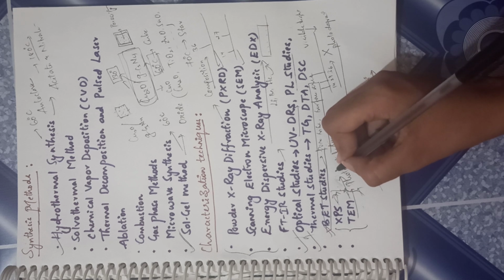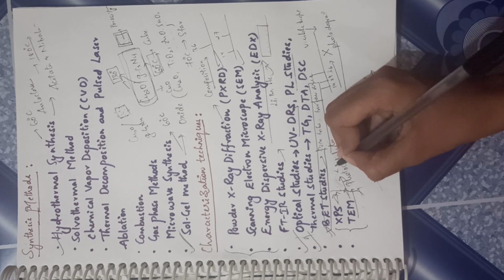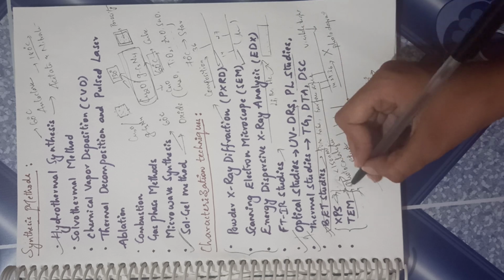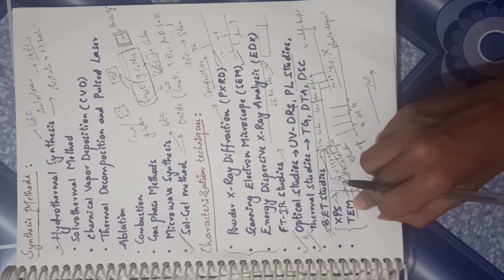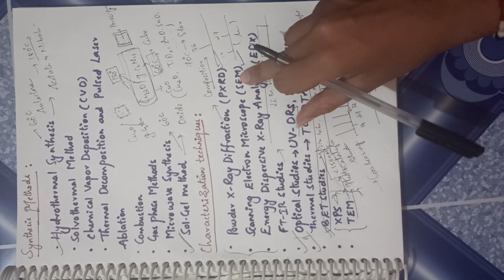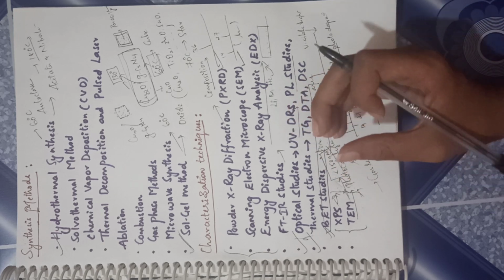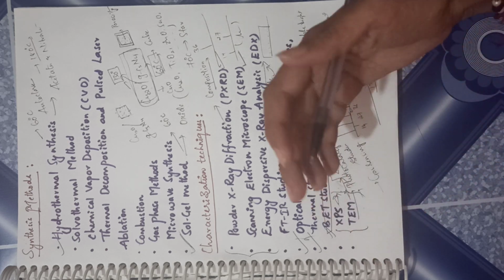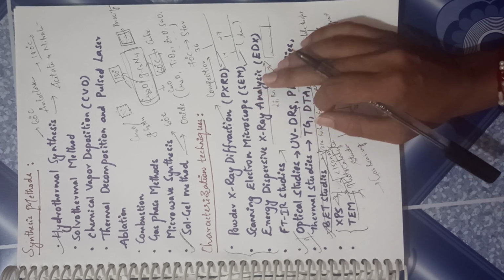Another point which we have to notice is that you can perform TEM only if the particle size is very small, let's say less than 150 nanometers. This is not the case with SEM. You can perform SEM even for microns, but for TEM you have to have a particle size of less than 150 nanometers. It is a sophisticated technique, and the sample preparation in TEM is really difficult when compared to SEM. So you cannot have 10-15 samples for XPS and TEM. The best, optimized sample has to be chosen and given for XPS and TEM characterization, whereas other characterizations are a little simpler. So this is all what I wanted to share, what I have learned in my PhD in these 2 years.